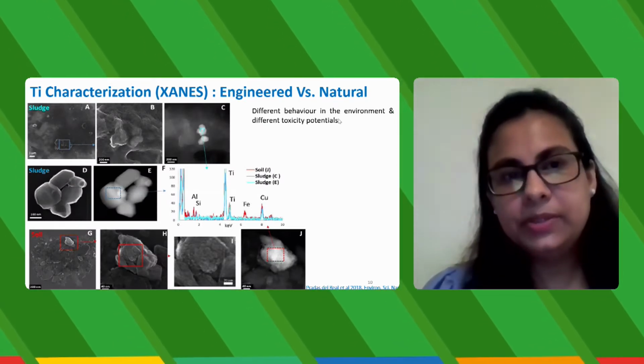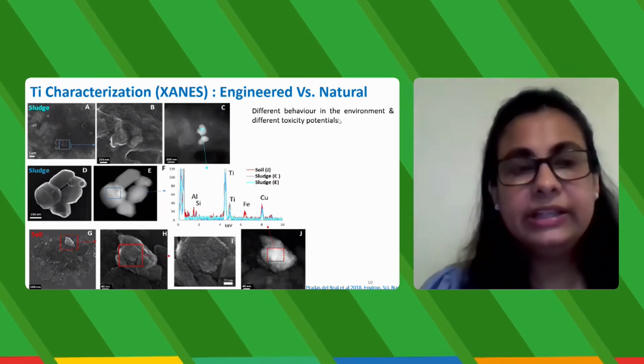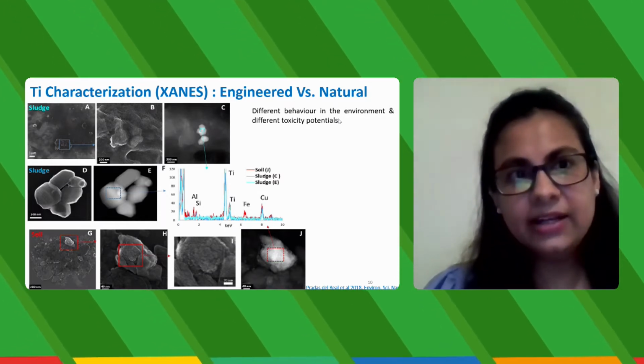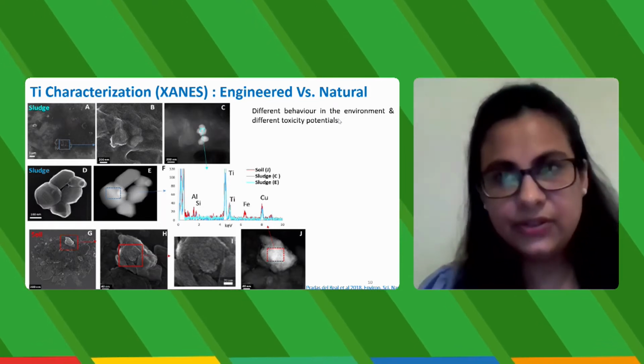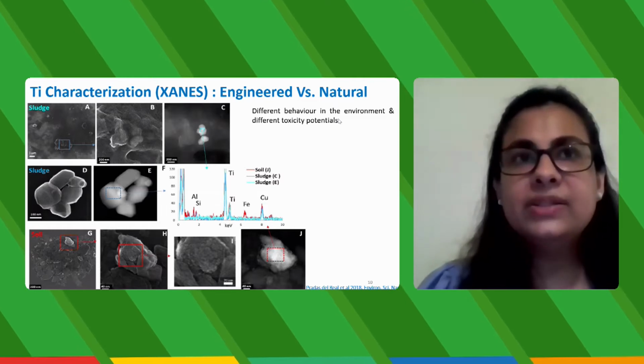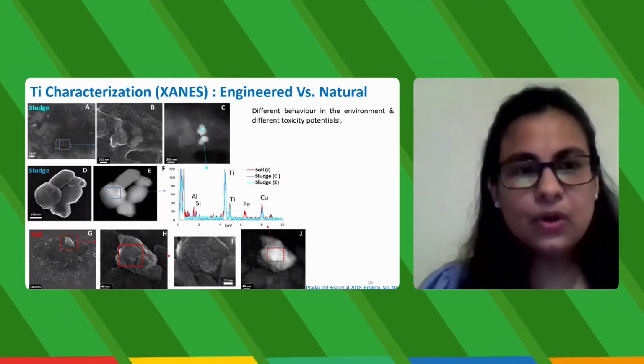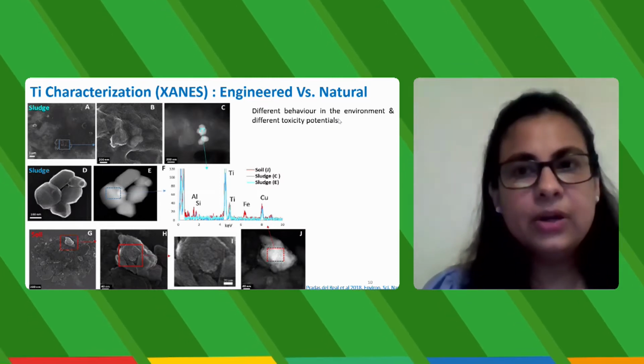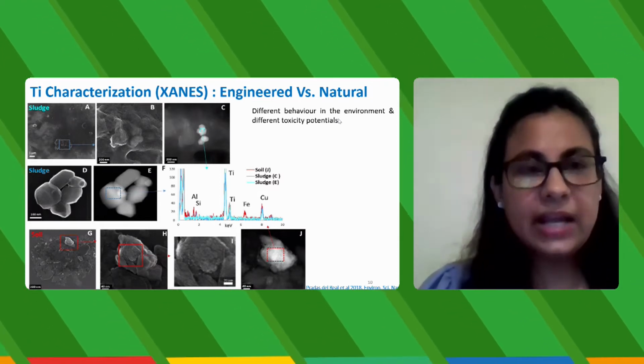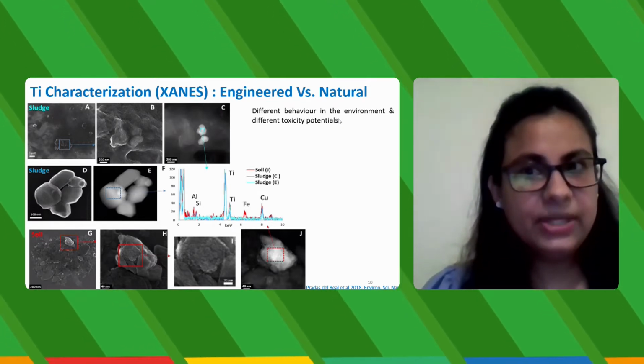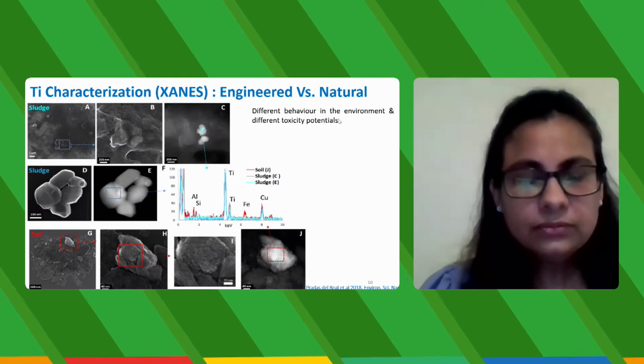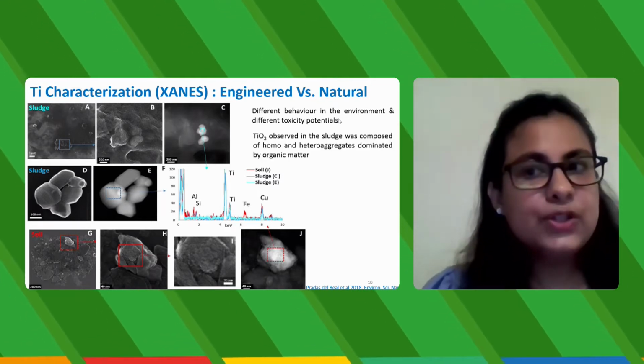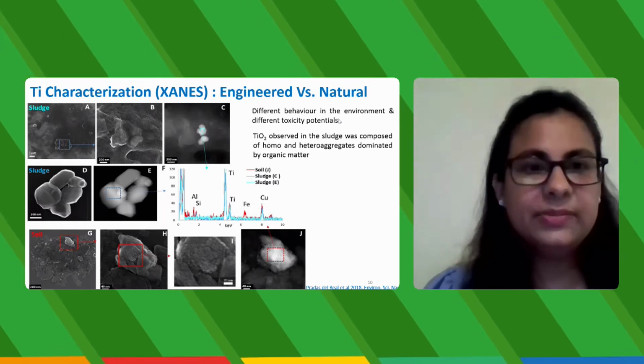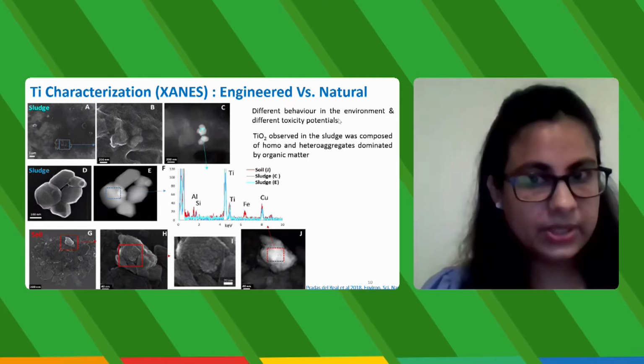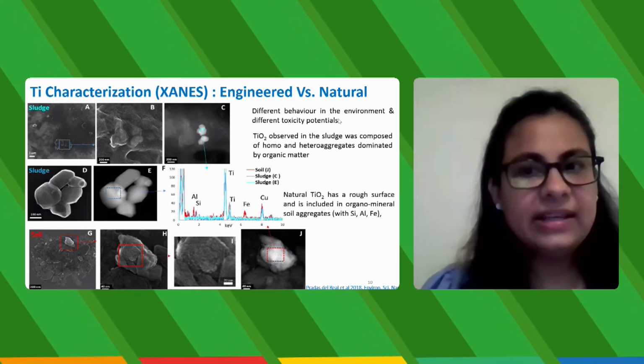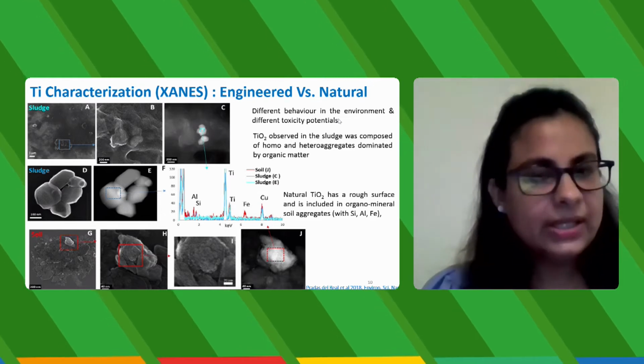Secondly, and now the most important part, it is very important and also equally difficult to characterize titanium and distinguish between which is engineered and which is natural, because as I said, we used an environmental matrix and did not do any artificial spiking. So we ran our XANES maps and found that there is a difference in the behavior of nano titanium and natural titanium. It is different in their toxicity and behavior. For example, the titanium observed in the sludge was composed of homo and hetero aggregates dominated by organic matter. So this is what we are talking about, engineered nanoparticles. And the natural TiO2 has a rough surface and is included in organo-mineral soil aggregates with silicon, aluminum, and iron.